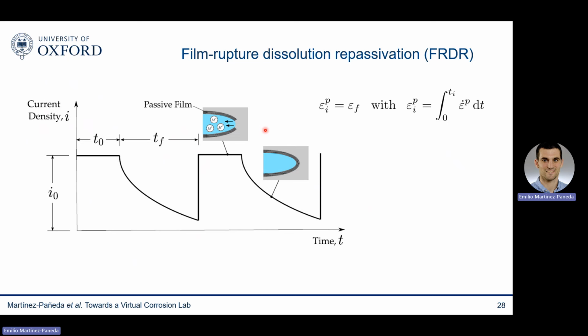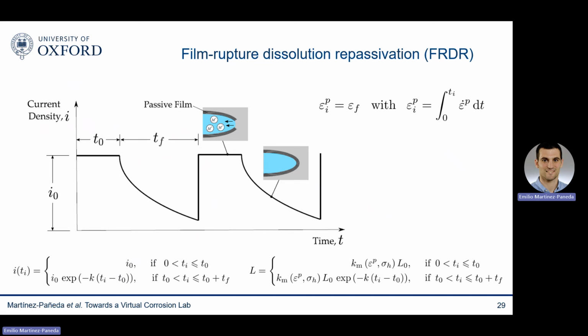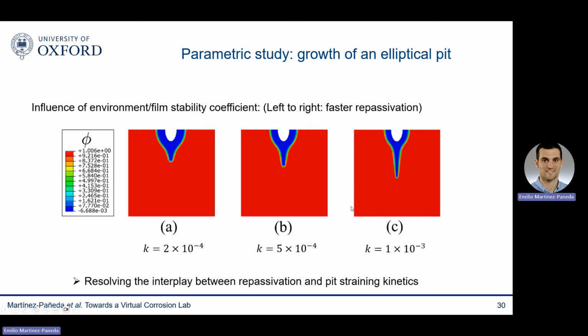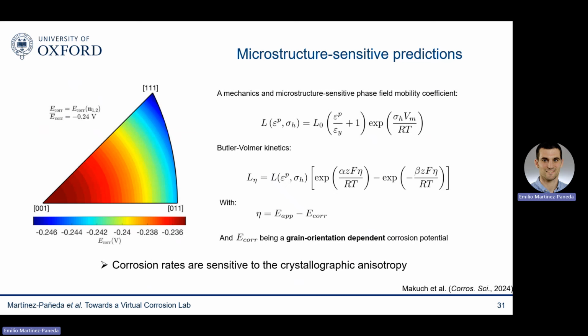And again, this is straightforward to incorporate into our model because we are solving a mechanical problem. So we know when the strains are large enough to cause film rupture. And exploiting the relationship between this mobility coefficient and the corrosion current density, we can again enrich the definition of this L coefficient to incorporate this film rupture, dissolution, repassivation mechanism. And then when you do that, basically you can run simulations that resolve the interplay between the straining kinetics and repassivation kinetics. And among other things, you are able to predict naturally the pit to crack transition, which is something that the community has been trying to do for decades.